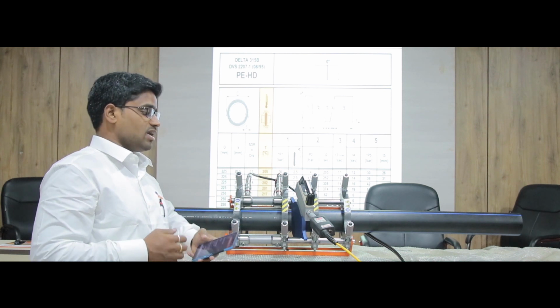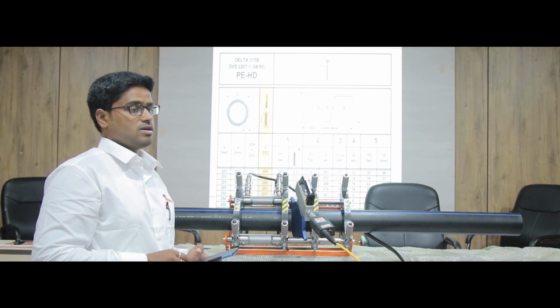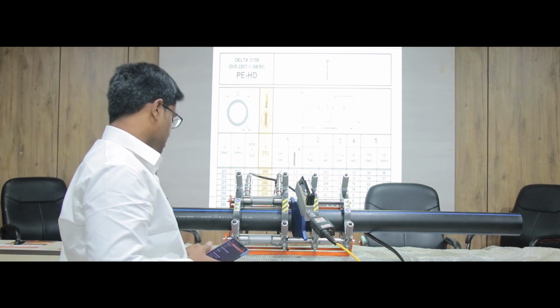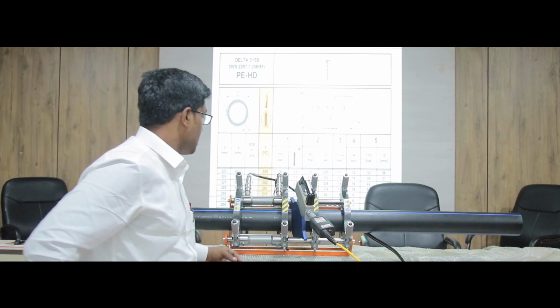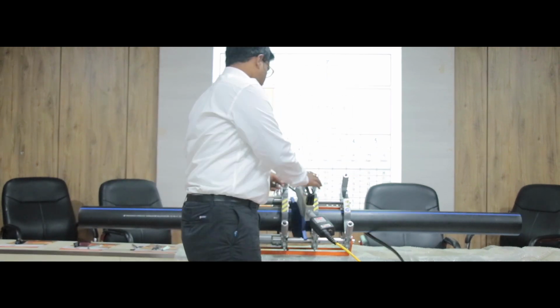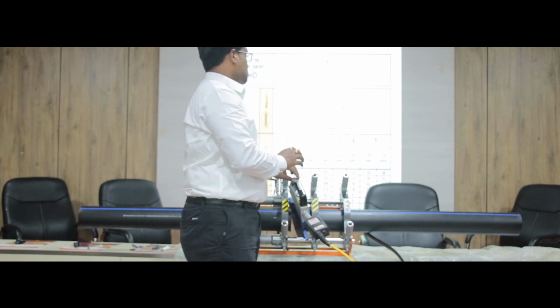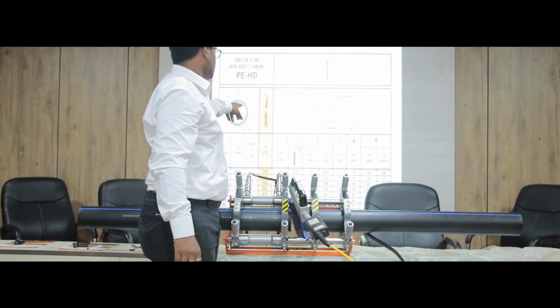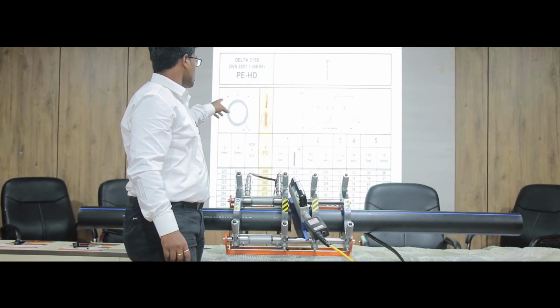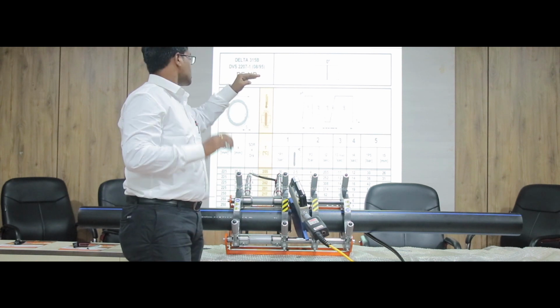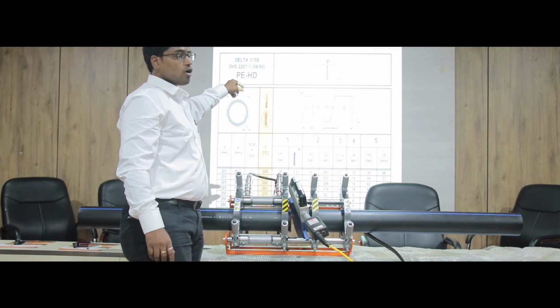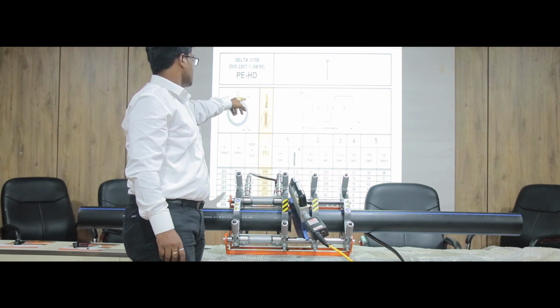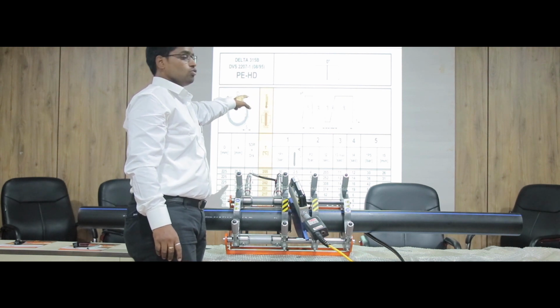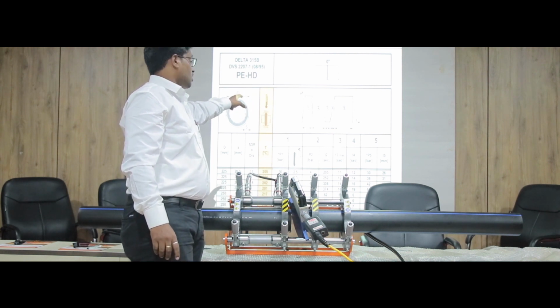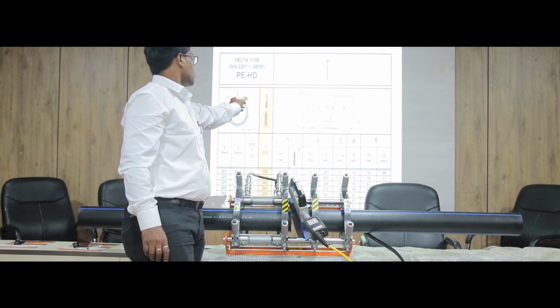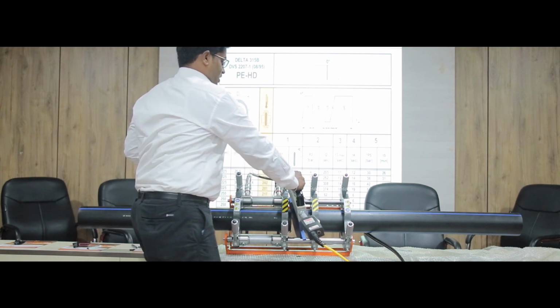Yes, sir. For time, we have to start a stop clock in our watch or something, and we have to maintain that. We engage the heating plate, and once after engaging the heating plate, we have to look for the bead size. Once the bead size is achieved, say 1 mm is achieved, we have to reduce the pressure to a value equal to or less than drag pressure. That is in the second phase, P2. Once that T2 time is over, we have to remove the heating plate.